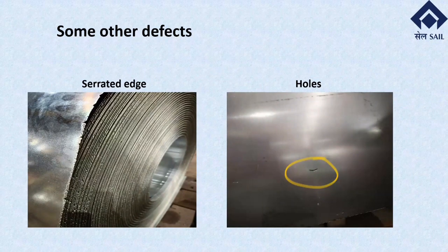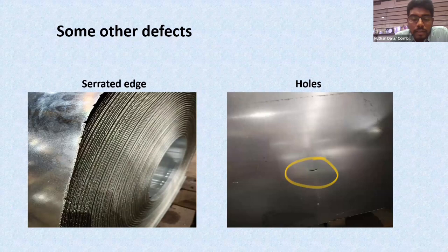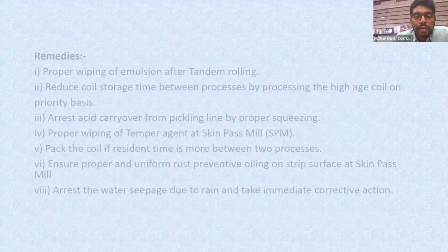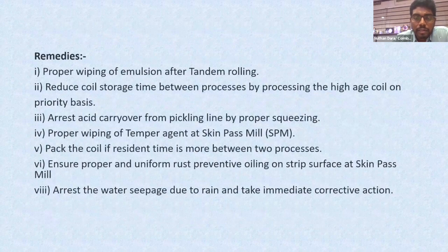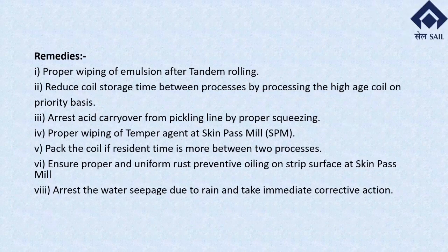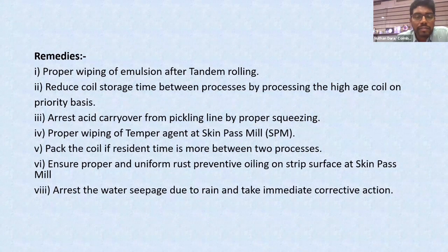Though this is corrected in one or two coils. Excuse me, sir. Yes, sir. Sir, I am Nutan from Coimbatore. Regarding rusting in CR, our customers here complain that on the CR coil, something is written with wet chalk, because of which it gets rusted. By the time the coil comes to Coimbatore, that portion is rusted. They are requesting that writing with wet chalk on the coil be avoided.